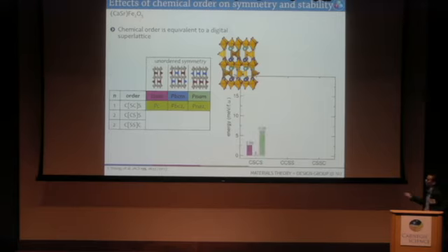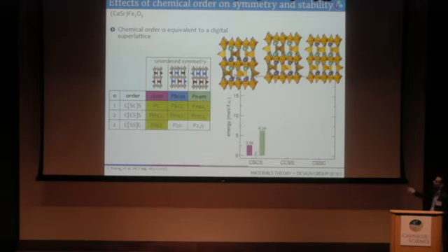We can compute the energetics, and what we predict from first principles is that this phase here, derived from the centrosymmetric one, should be the equilibrium or ground state structure, in close competition to the PC structure. Two other variants that maintain this stoichiometry are these two superlattices here. And you can see in this case, we have two calciums and two strontiums. And those two calciums and strontiums can either bridge the tetrahedra like this, or they can bridge the octahedral units like that. And that's what's indicated by these two lines here. In most of these cases, you find that the number then of polar structures, or structures without inversion symmetry, increases. And these are the energetics then of those phases.